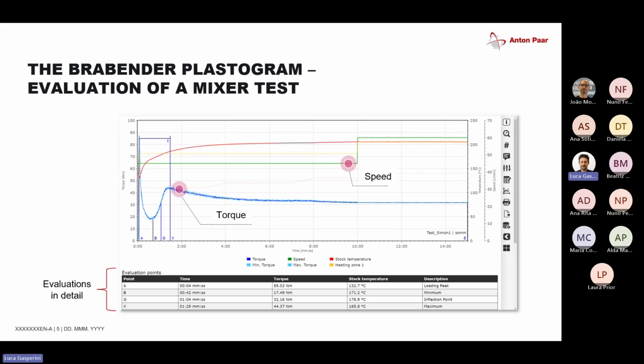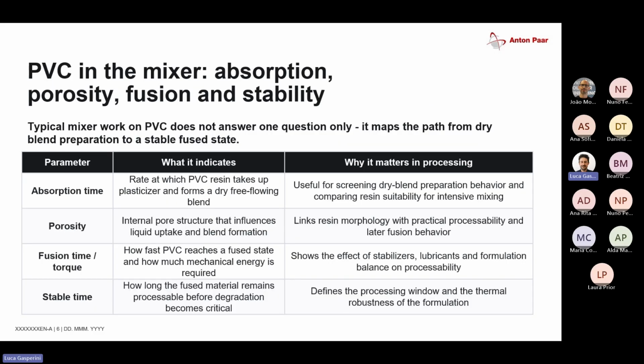Then the software also automatically evaluates your fusion time, which is defined in the standard from the loading peak until the maximum of the torque level. So, especially for PVC, fusion time, like I said, is a very important parameter when it's about determining the optimal process window. But there are also other parameters, like, for example, the porosity and the absorption time when we talk about the plasticizer absorption of a raw PVC.